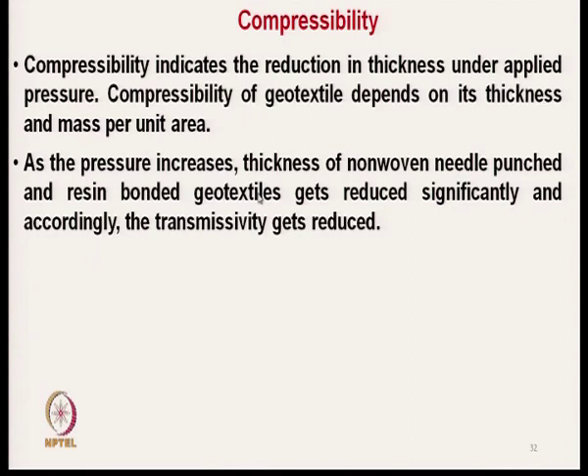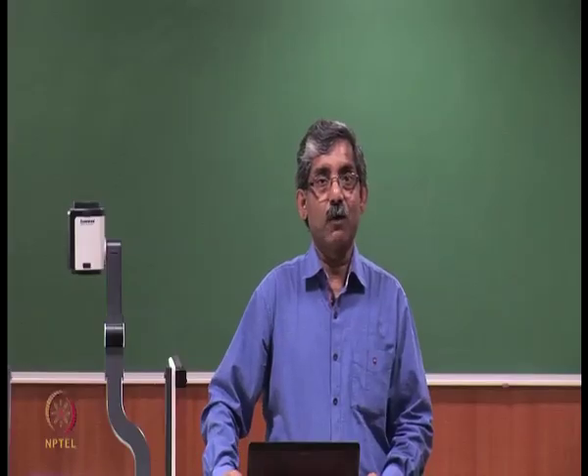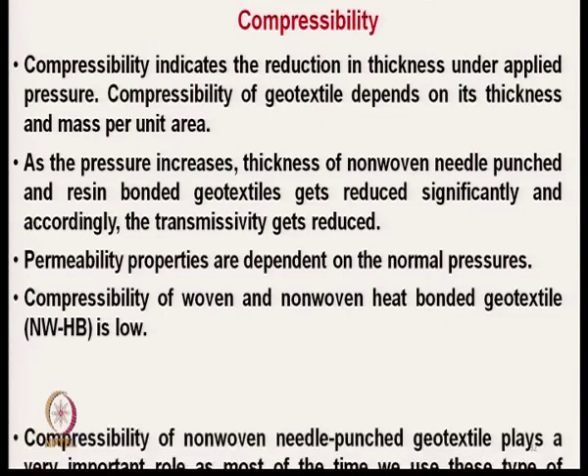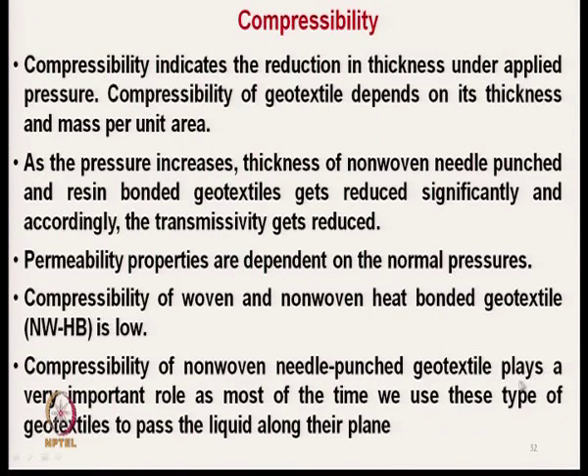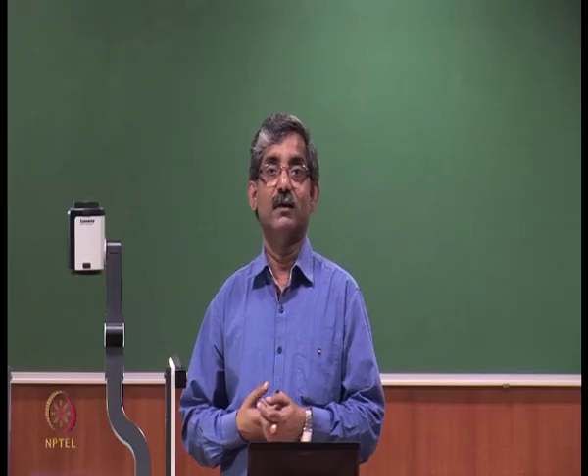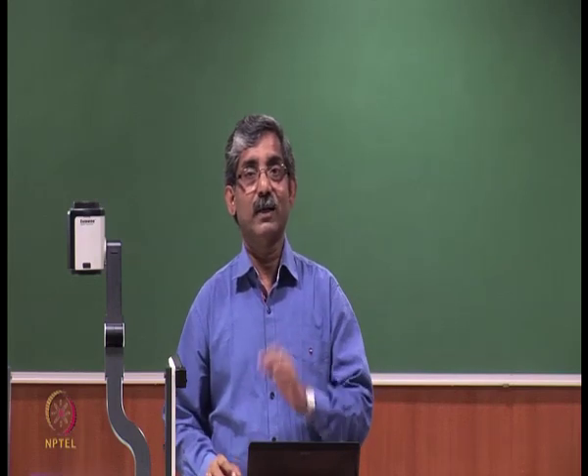The compressibility of geotextile depends on thickness and mass per unit area. As pressure increases, the thickness of nonwoven needle-punched and resin-bonded geotextiles gets reduced significantly, and their transmissivity is affected. Permeability properties are dependent on normal pressure. Compressibility of woven and nonwoven heat-bonded geotextiles is lower than that of needle-punched geotextiles. Compressibility of nonwoven needle-punched geotextiles plays a very important role since most of the time we use them for drainage characteristics.